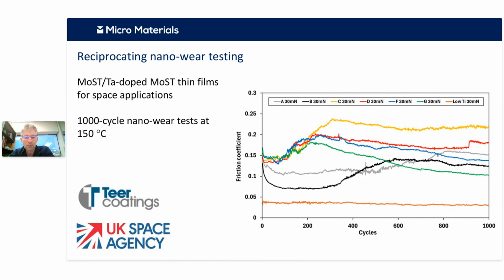And in the results, you can see on the right there, that's essentially just showing you have the stability to do these 1,000 cycle tests quite easily and look at things like the friction coefficient and the depth and see how those vary as a function of cycles. So in this case, you can see for various different coatings that there's a big difference in stability in terms of the number of cycles before the friction coefficient goes up as the film starts to fail.